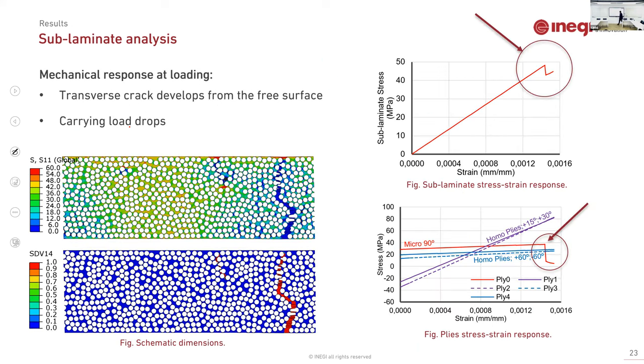Let's see in more detail what happened. If we apply loading in the lateral direction to the sublaminate model, what will happen? Of course, failure will appear. The failure will appear depending on the local arrangement of the fibers. This fiber arrangement is generated with a random algorithm. It's not a clear starting point. The opening of the failure at the free surface is higher than in the interior, at the interface with the adjacent layer. That is clear.